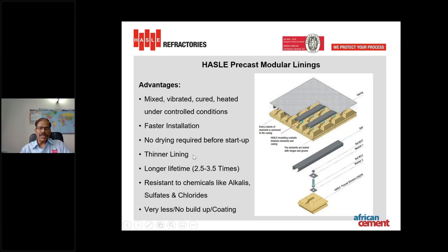We can also reduce the lining thickness. Suppose you want to reduce the lining thickness from 300 or 350 millimeters to something less, we can reduce it up to 185 millimeters. This provides a longer lifetime, around 2.5 to 3.5 times. And this precast lining is resistant to chemicals like alkali, sulfate and chlorides. Hence, it leads to very little or no buildup coating on the surface of the precast lining.